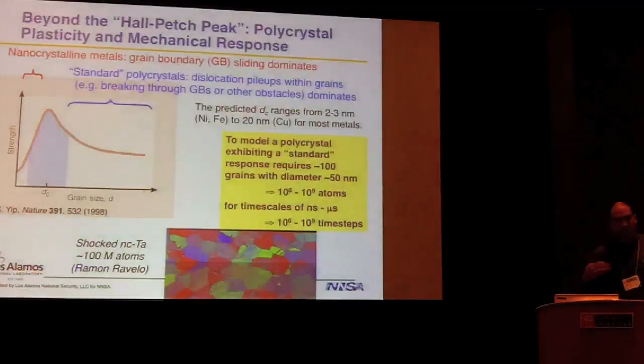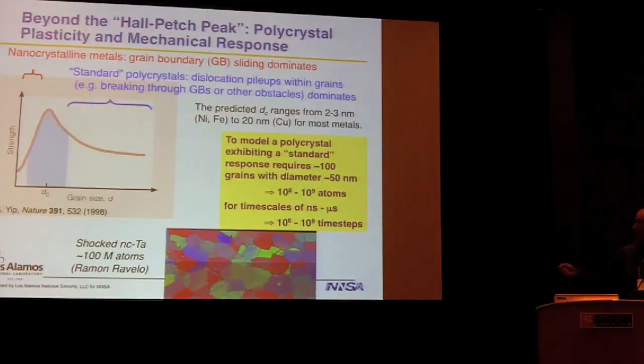under these loading conditions. So these single-scale MD simulations can be pushed forward further and further, and there's a need for larger and larger scale. In particular, as we look at these polycrystalline samples, a typical material is composed of different grains, different orientations. If you look at marble or other materials, you can see the grains. In metals, they're typically not visible to the eye, but these microscopic grains and this collection of grains determines the material response.